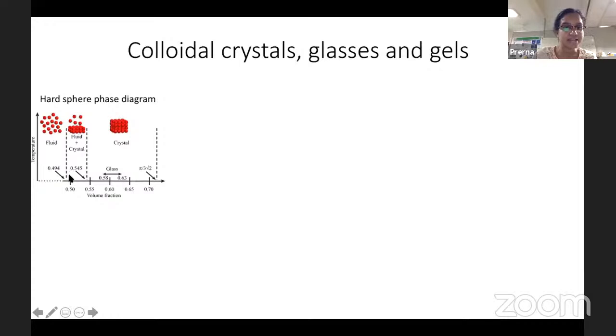What happens is that above a critical volume fraction, which is about 0.55, you see that the equilibrium phase is a crystal. Now this is surprising. Remember I said that in hard sphere systems, the equilibrium phase is the one which has the highest entropy. And so in this volume fraction, crystal has the highest entropy. So how do you reconcile this with your naive understanding of order and disorder and how they connect to entropy?